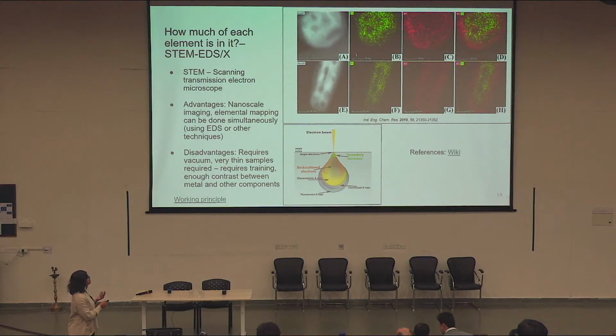And when I start measuring the X-rays that are emitted from my sample, by using the energy of the emitted X-rays, I can say where iron is present and where manganese is present. And I can put these two mappings on top of each other, and I can get information about where exactly manganese and iron are present when there is a compound of manganese and iron. So this is for the spherical particle and this is for the nanorod.